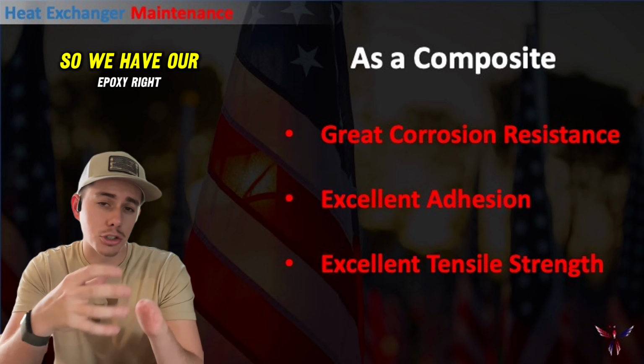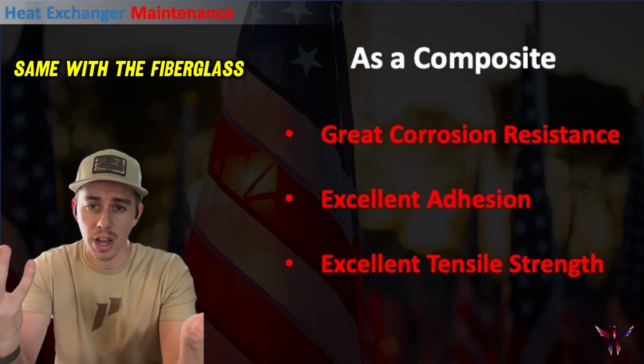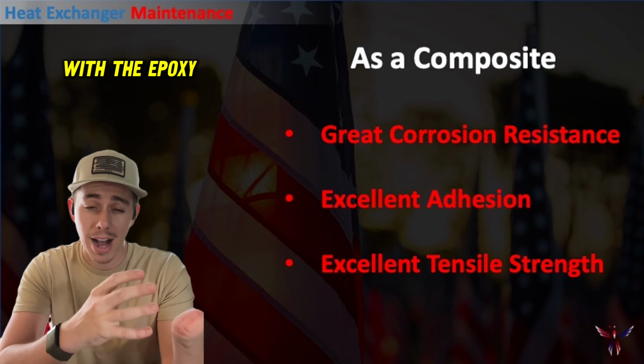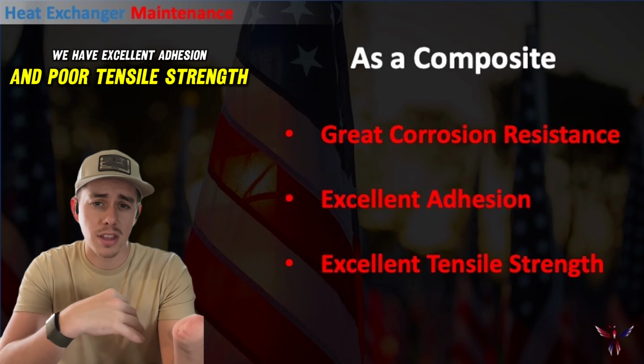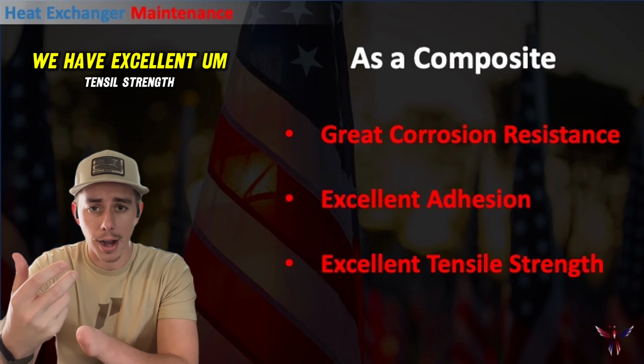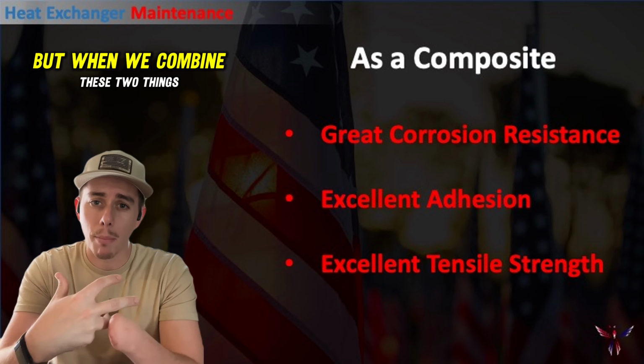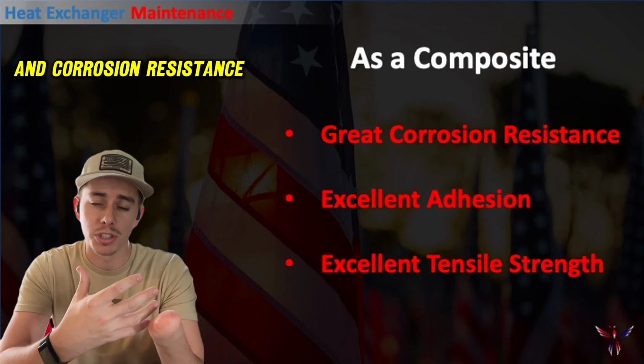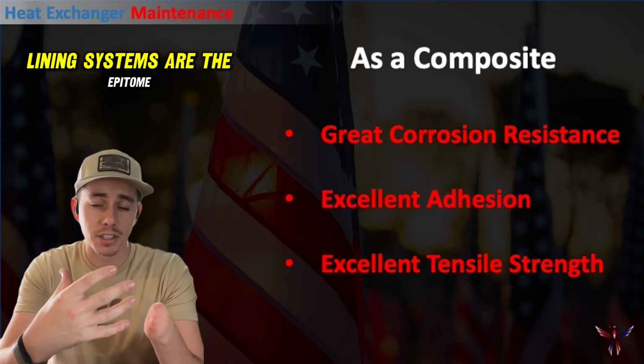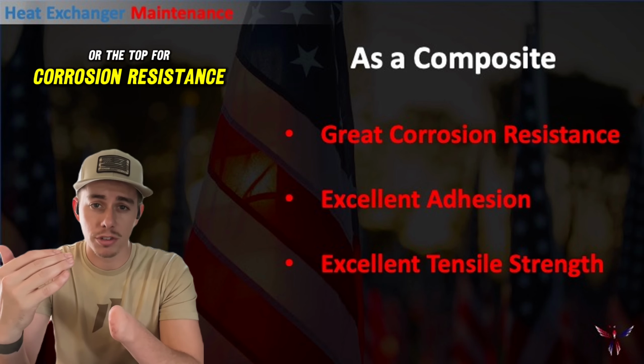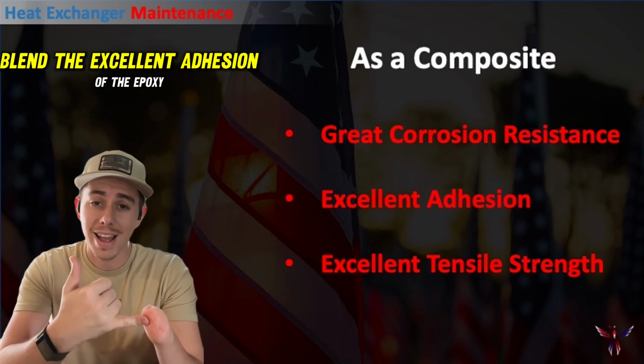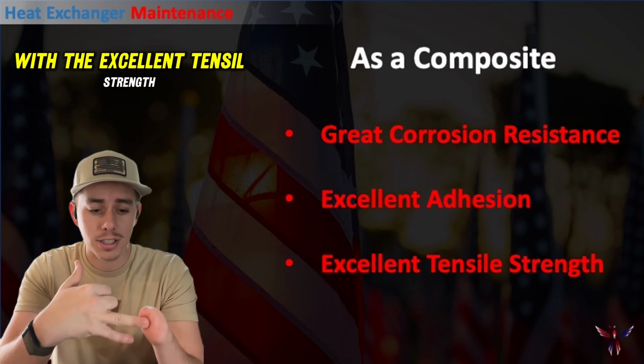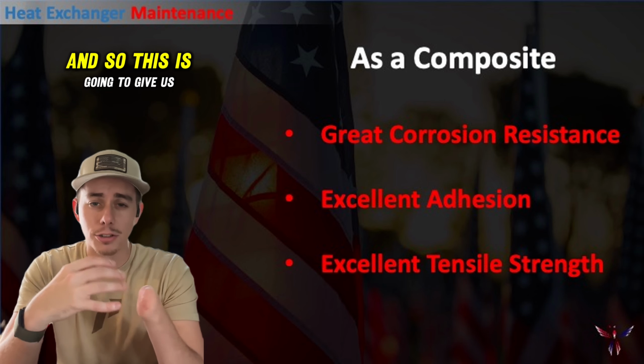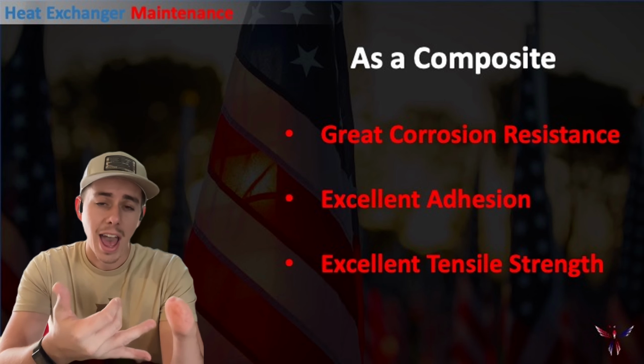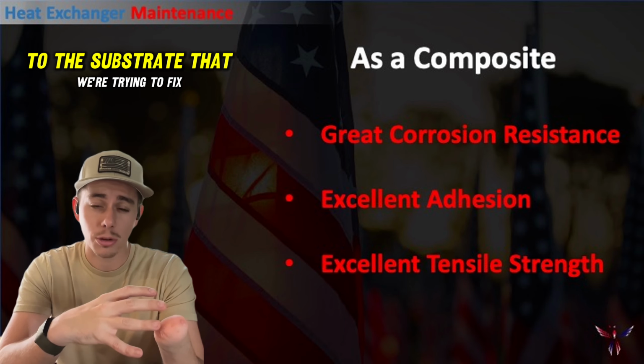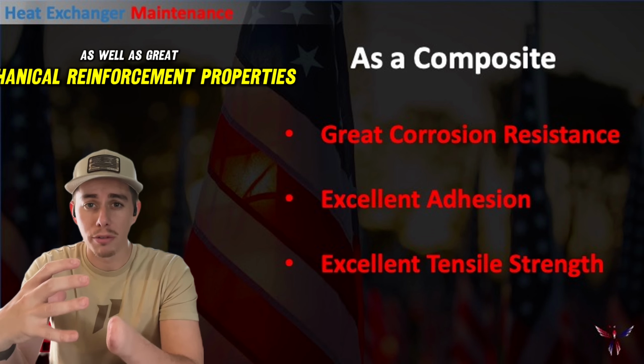Now, as a composite, so we have our epoxy, right? Great corrosion resistance, same with the fiberglass. But with the epoxy, we have excellent adhesion and poor tensile strength. And with the fiberglass, we have excellent tensile strength but poor adhesion. But when we combine these two things, we get a bump in corrosion resistance, as a lot of glass flake filled lining systems are the epitome or the top for corrosion resistance. And then we get to blend the excellent adhesion of the epoxy with the excellent tensile strength of the fiberglass. And so this is going to give us all around corrosion resistance, excellent adherence to the substrate that we're trying to fix, as well as great mechanical reinforcement properties.